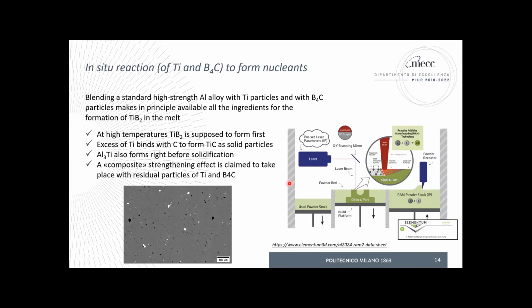Okay, actually, apart from the commercial name, which is not important for us, the main concept is that they promote an in situ reaction, making available what we need right in the liquid phase. So again, the story is always the same. We promote at very high temperature the generation of TiB2, then the excess of titanium binds with carbon, which is an important issue, to form titanium carbide in order to keep carbon apart from the game of solidification. And then Al3Ti forms with the excess of titanium.